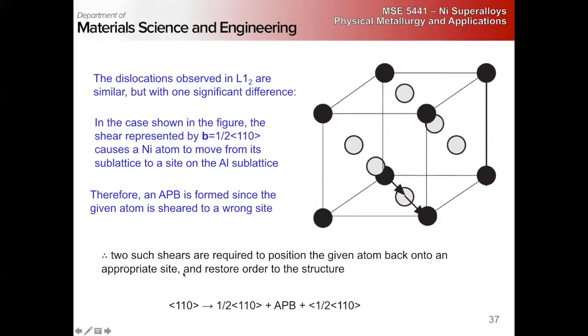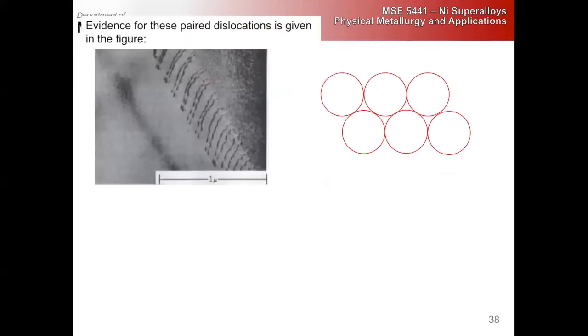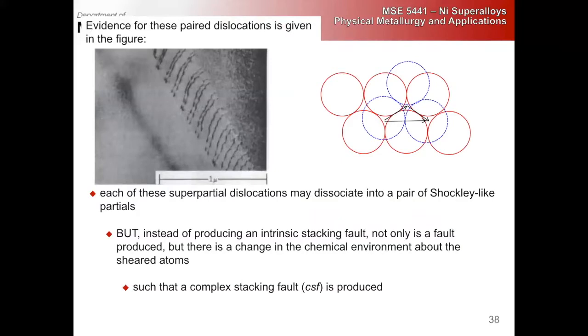So a full dislocation of type <110>, right? Generally, we have 1/2<110>s that are full FCC dislocations, partials in the L12 with an antiphase boundary separating them. All right? So each of these superpartials, though, can also dissociate into a pair of Shockley-like partials, right?